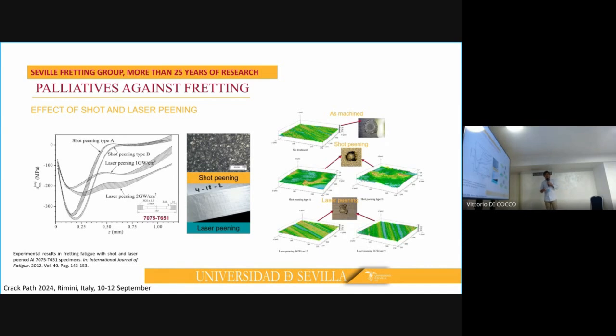We also had an important effort in order to understand the behavior produced by shot peening and laser peening. Perhaps the first thing that comes to your head when you think of shot peening and laser peening is the residual stress and also maybe the work hardening, because this is the main feature that produces the improvement in the plain fatigue case. But an important thing is that in fretting, the contact surface condition matters.